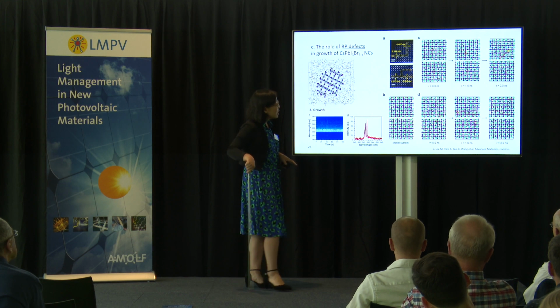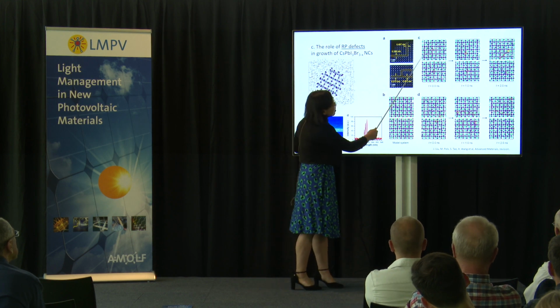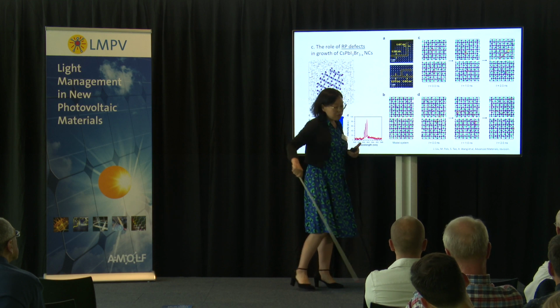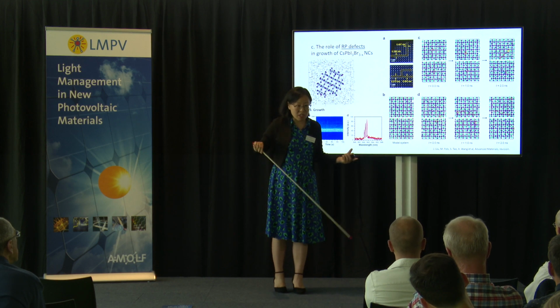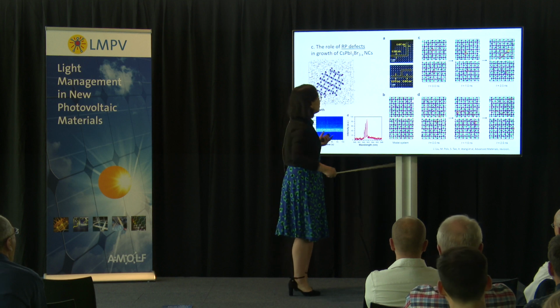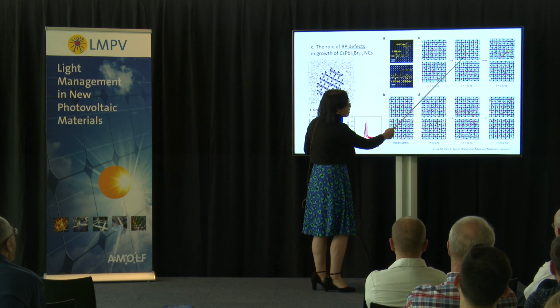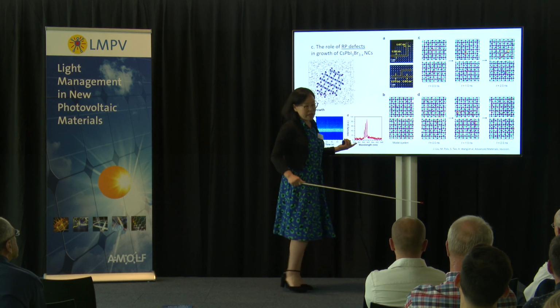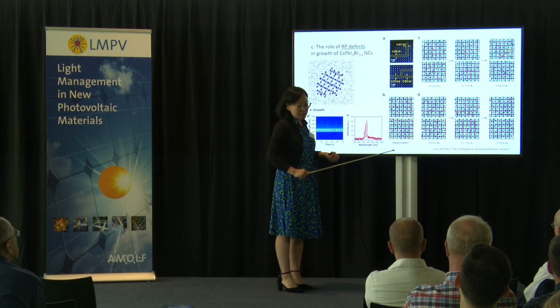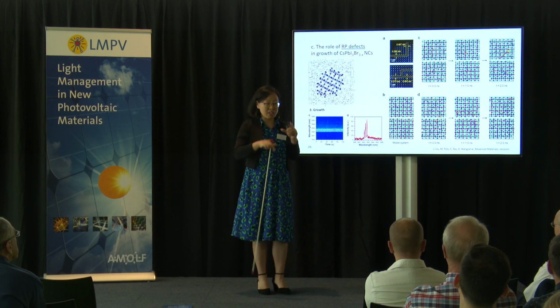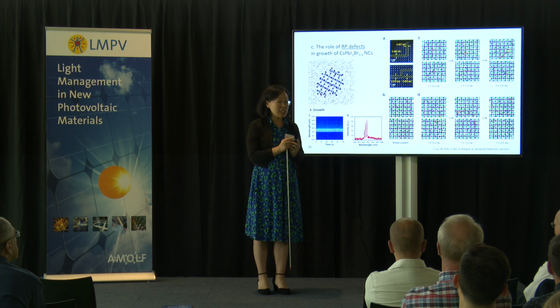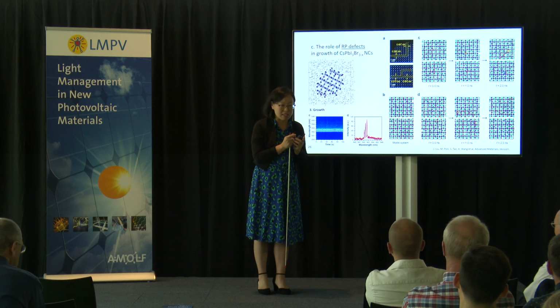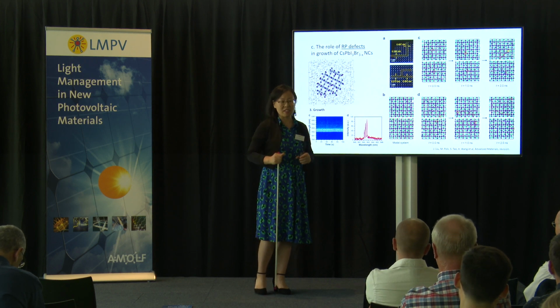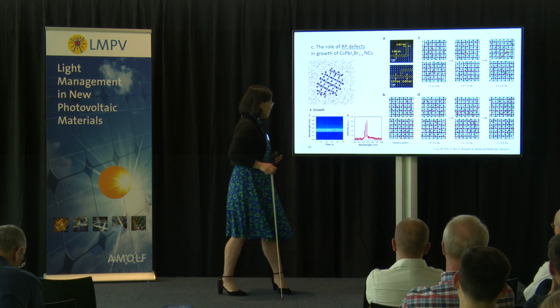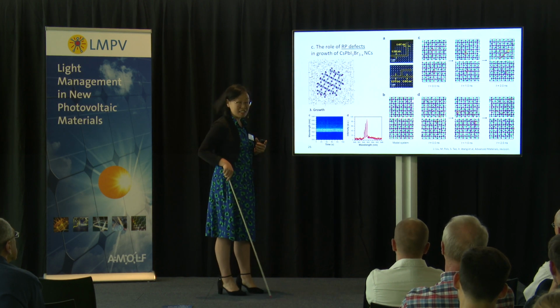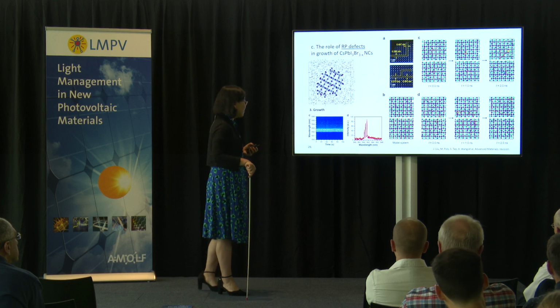But if we take into account the defect inside the grain, we want to see if the defect will migrate across the grain. If we do this simulation, you actually see no matter where we start the defect, they go nowhere but stay in the domain. That means once your film forms, once you have the RP domain, the composition nanodomain is protected, and it's always having the same emission peak. This simple simulation demonstrates this effect.